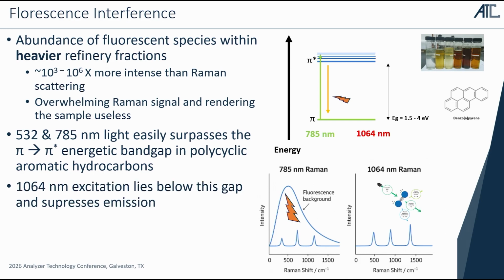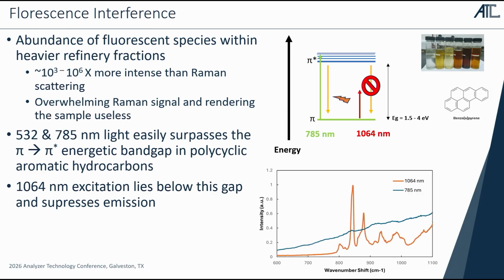So the primary and kind of an interesting workaround to this is by using light of a longer wavelength or of a lower energy. Essentially what this does is you have a lower energy excitation, and so those electrons are unable to surpass that band gap energy, that energetic gap between the ground state and the excited state is no longer accessible. And so essentially you're blocking out that radiative relaxation pathway that is interfering with your Raman signal. And so in doing this, you're essentially eliminating that absorption and re-emission process, and what you're left with is the peaks of interest that were there all along in the fluorescence samples. They were just invisible due to the fluorescence process.